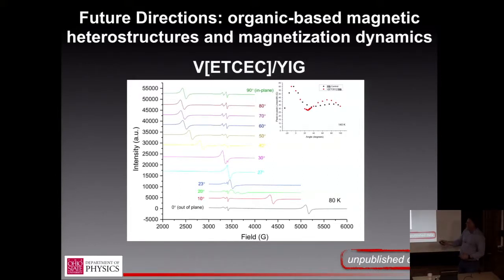So out here they're decoupled, but as they get closer, these resonance frequencies start to line up, and you'll notice that the organic, multi-lined response collapses into a single line that's significantly narrower than the YIG. This is actually far away interaction and changing the way that the subsystem behaves. It isn't just like two lines that pass through each other. Exactly. So they're not just spectrally tuning through. We think there's strong evidence of interaction and coupling, and we need to do more work before we can say this conclusively. But this could be evidence of exchange coupling between the organic-based magnet and the inorganic-based magnet, which would be very exciting. I don't know of another case where that's been demonstrated.